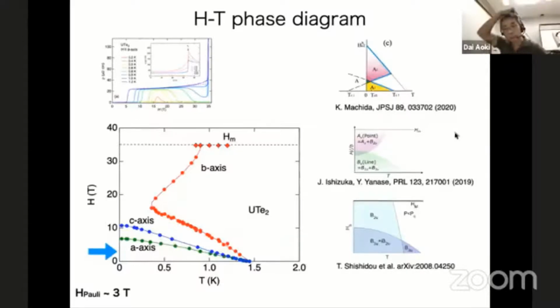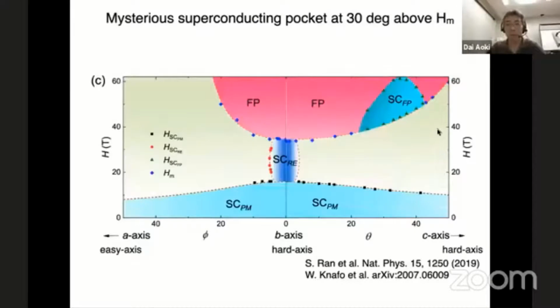Another interesting point is that this result was first reported by Shen Ran. This is HC2 versus field angle. This is the B-axis, the hard axis. When we apply the field along the B-axis, we observe the reentrant superconductivity in this region. And at the metamagnetic transition, in the spin polarized phase, there is no superconductivity. But if you rotate from the B-axis to the C-axis, this means from the hard axis to the hard axis, the superconductivity appears again at around 30 degrees. So this is really mysterious.